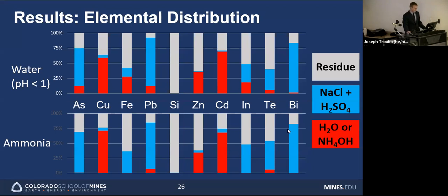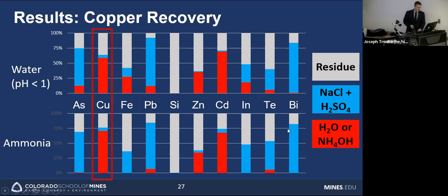So I'll skip to the results. Here you see an elemental deportment diagram, also known as the elemental distributions. I want to mention that the water leach naturally forms an acid, roughly a pH of around 1. There's a lot going on here, so I want to highlight for you the copper recoveries. For ammonia, the copper recovery was around 70%, 71%, whereas for water leaching, roughly 60 to 65% of copper was recovered. This means that ammonia leaching did result in better copper recovery.